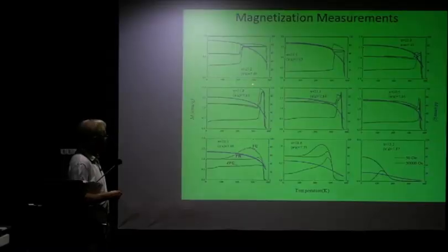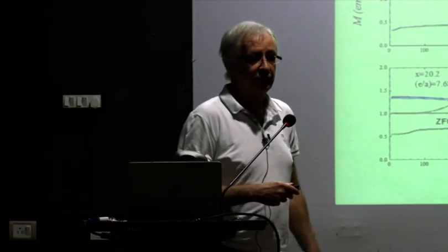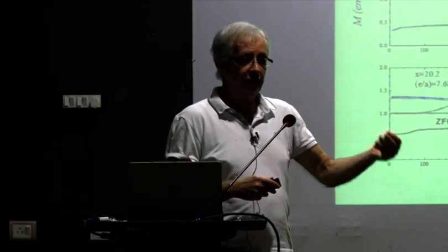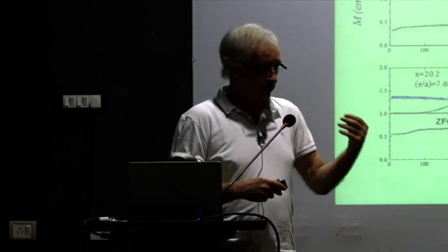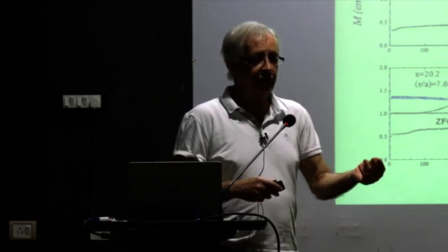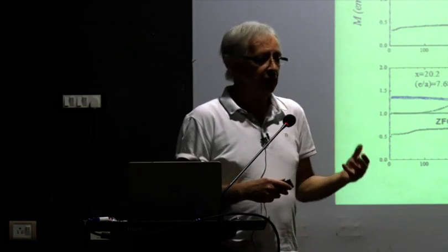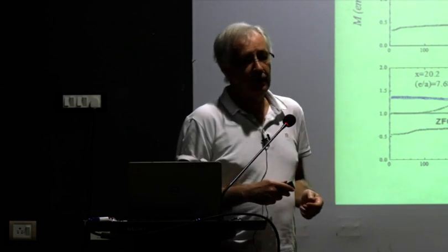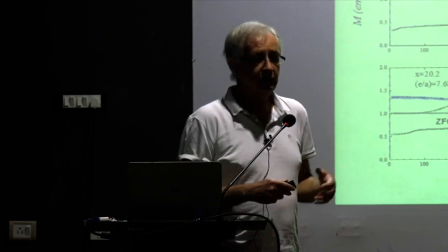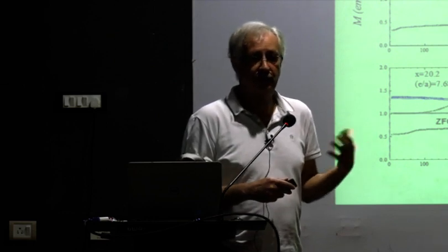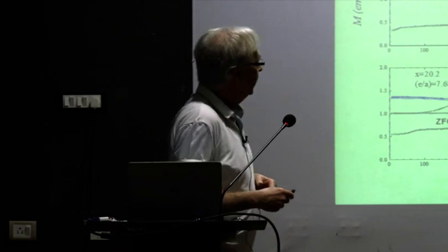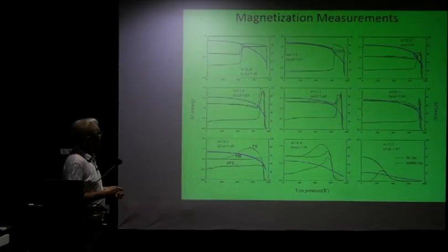And we have here magnetization data that is taken in 50 Oersted and in 5 Tesla, in 2 different magnetic fields. One at very low magnetic fields, where you try to see the intrinsic ordering, whatever is in the sample, the magnetic ordering, and then you pump in the field and you measure in saturation to extract information on the magnetic moments and things.